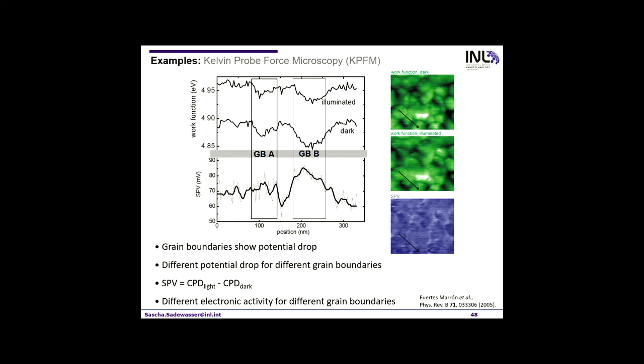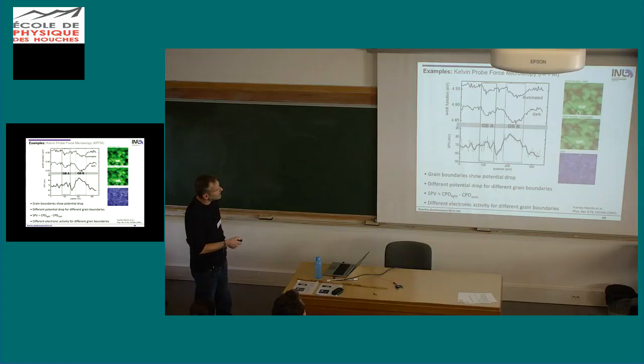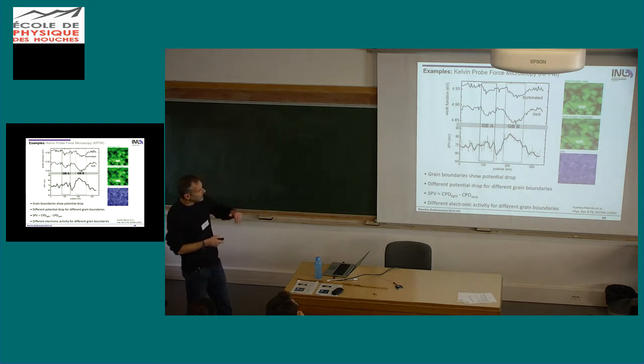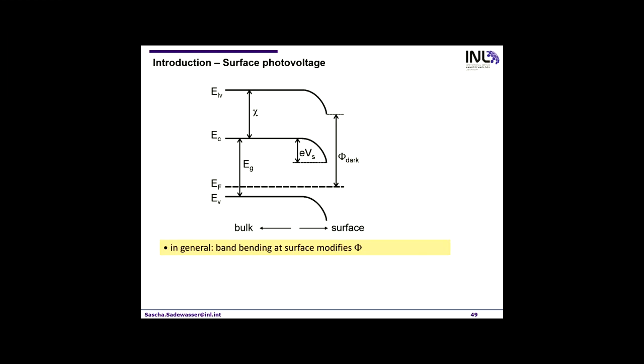So if I go one slide further, if you take this line scan here, you can see that in the dark we see this kind of behavior, a drop at the grain boundary. So this is the band bending that we saw before, and a larger drop at this other grain boundary here. But under illumination, everything shifts up. So there's a surface band bending, and I think this is on this slide.